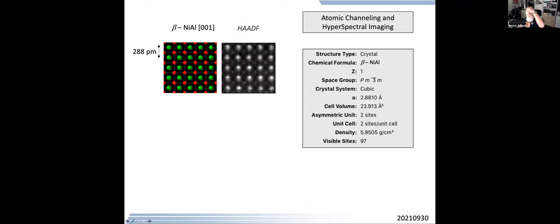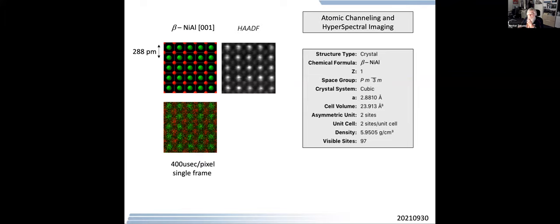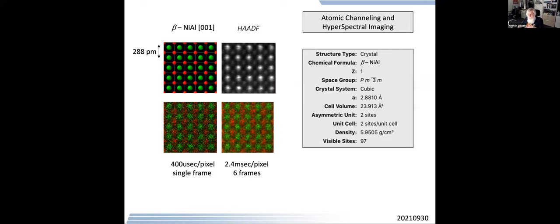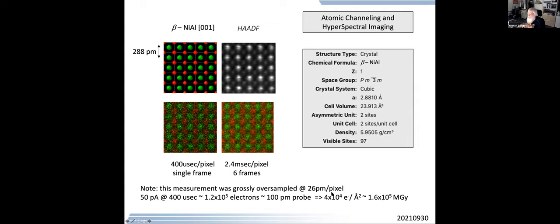This is a single frame capture where we're spending a few hundred microseconds per image. And at the same time, we can acquire with the HAADF at 400 microseconds per pixel, which is pretty quick, a complete hyperspectral image. And of course, if I do multiple frames, I can average it out and get a little bit better. Now, this particular image is oversampled, because I'm doing 26 picometers per pixel. I don't need anywhere near that. I can instead spread my beam out a little bit. I don't need such a high definition of that.